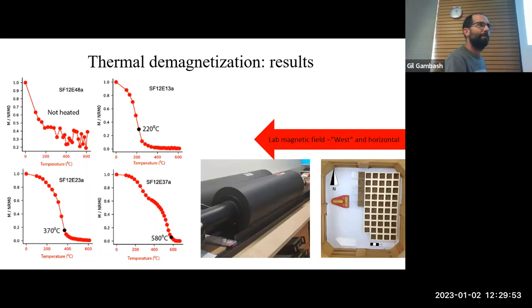I won't go into the mathematics here, but this is how we estimated the ancient heating temperature. For every one of these, we estimated the ancient heating temperature, and you can see that the knee is more or less here. This one recorded the magnetic field at 220 degrees, and the magnetic moment was erased a little bit, and one step above 220 is the knee itself. Here, 580, 370. So there's a very good correlation in general between the temperature at which it was recorded and the temperature at which it was erased, which is not surprising.